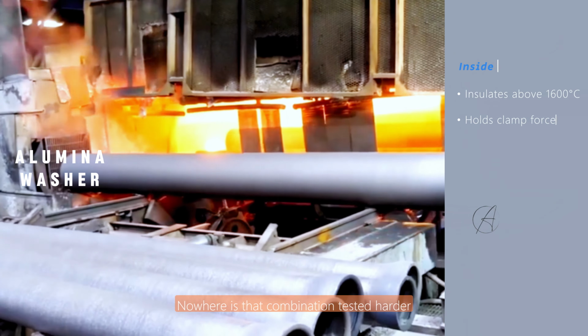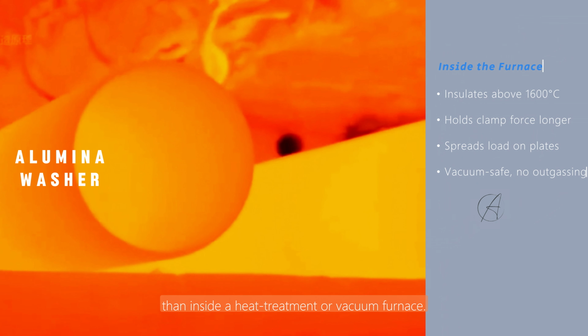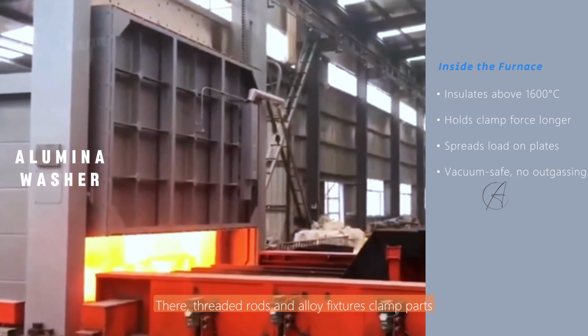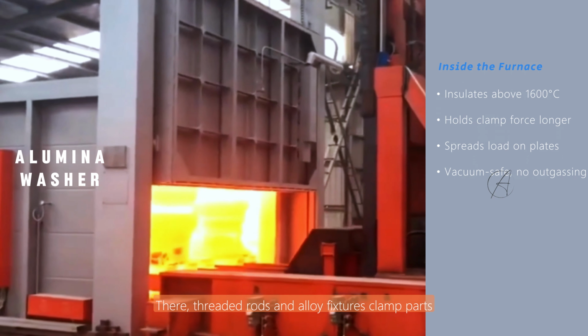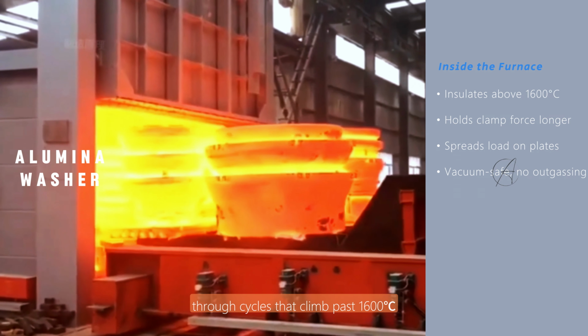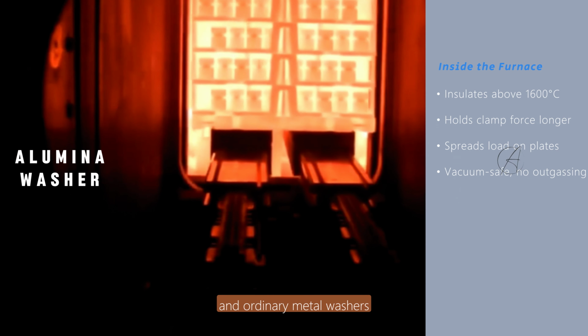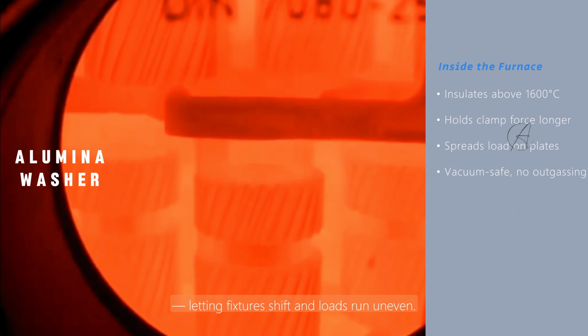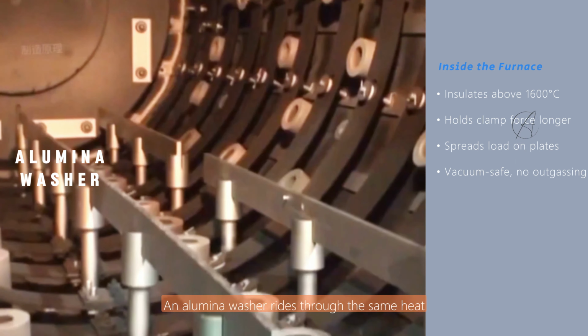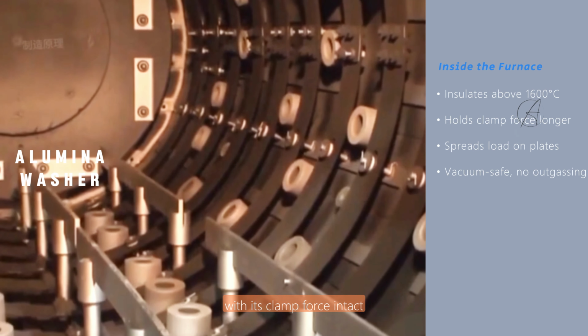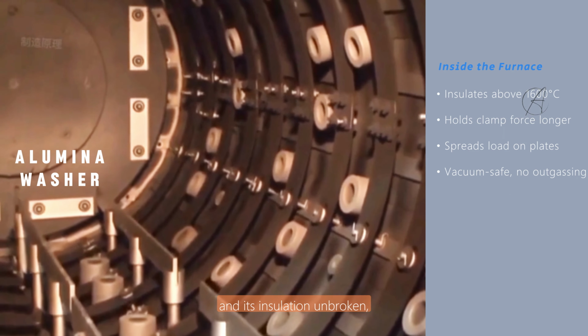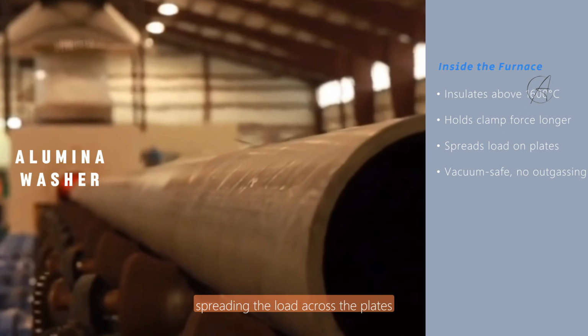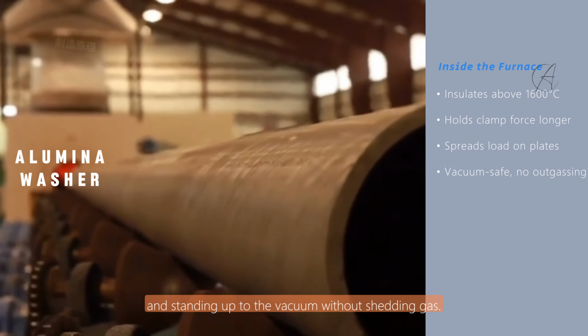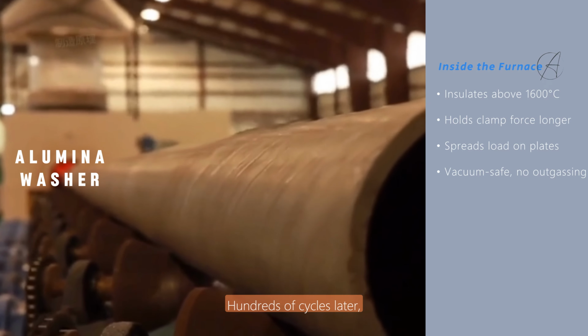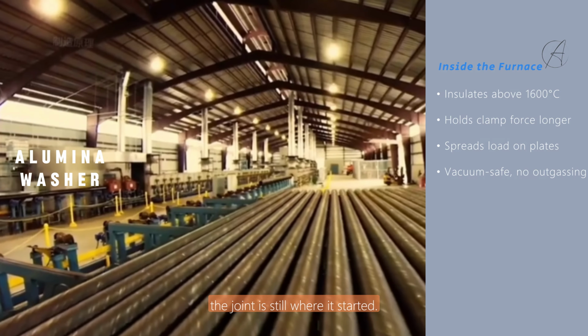Nowhere is that combination tested harder than inside a heat treatment or vacuum furnace. There, threaded rods and alloy fixtures clamp parts through cycles that climb past 1600 degrees, and ordinary metal washers soften, oxidize, and lose their grip, letting fixtures shift and loads run uneven. An alumina washer rides through the same heat with its clamp force intact and its insulation unbroken, spreading the load across the plates and standing up to the vacuum without shedding gas. Hundreds of cycles later, the joint is still where it started.